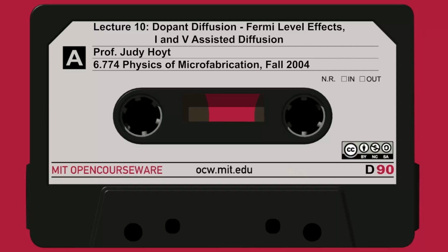They had a background concentration of n-type dopant that they created with, say, arsenic, and then they looked at diffusion of phosphorus underneath it. The Fermi level was constant in each of these samples. They got this triangle, and the electron concentration was 10 to the 19th here, going all the way up to low 10 to the 20. And then they extracted the diffusivity of the phosphorus as a function of the background electron concentration.